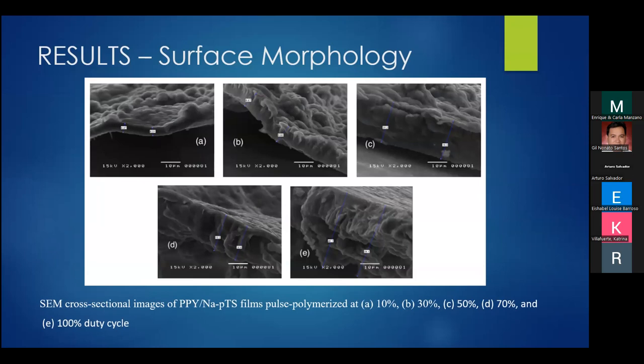the SEM micrographs of the five samples grown at different duty cycles: 10% in figure A, B at 30%, C at 50%, D is 70%, then the SEM shown in figure E is for the film grown at 100% duty cycle. So films A, B, C, and also D show globular structures, which is typical of conducting polymers. But we notice that the film grown at 100% duty cycle has a more flaky structure, and it is more porous.